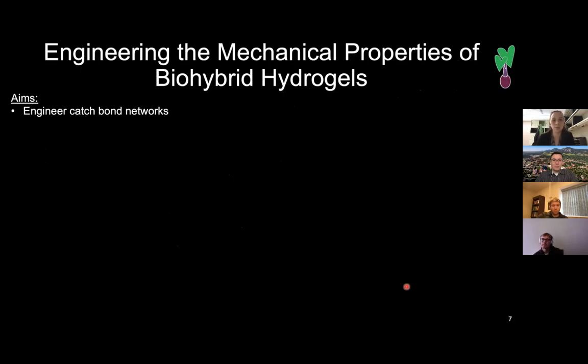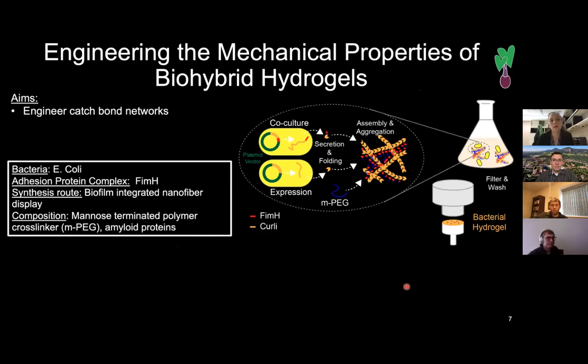So really going to do this through engineering these catch bond networks through this system called the biofilm integrated nanofiber display system, which is an E. coli where we will have a plasmid vector of this complex, the FimH complex, where FimH is a catch bond adhesion protein that's used by E. coli to actually cause urinary tract infections. So it's been shown that under shear, it increases in strength, and that's part of the reason why they're so infectious. And so we're going to use these catch bonds, these FimH behaviors, and then attach them and functionalize these amyloid proteins that can self-assemble into protein polymer-like strands, and then have these mannose PEG, which is polyethylene glycol, if we can control the architecture, where the end linkers are these mannose, which is what FimH binds to.